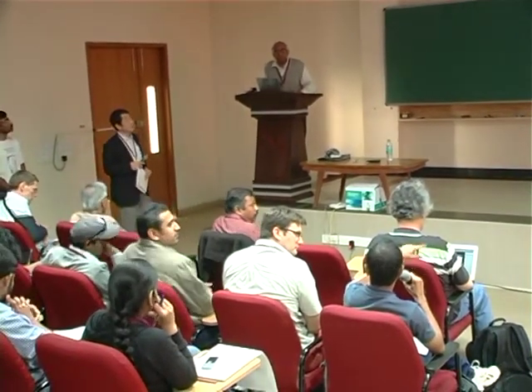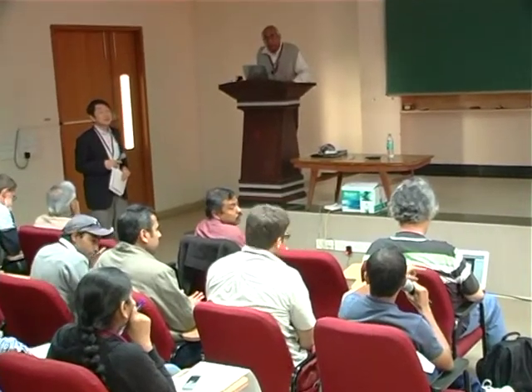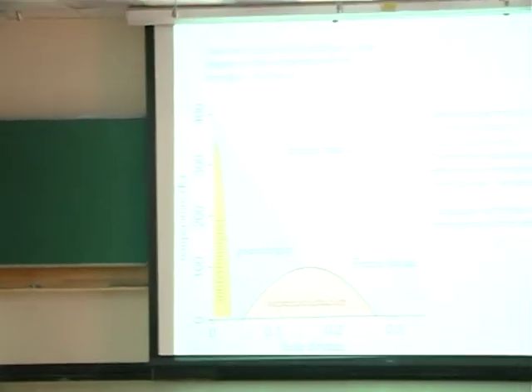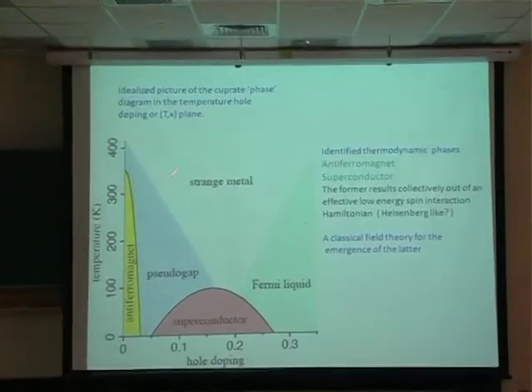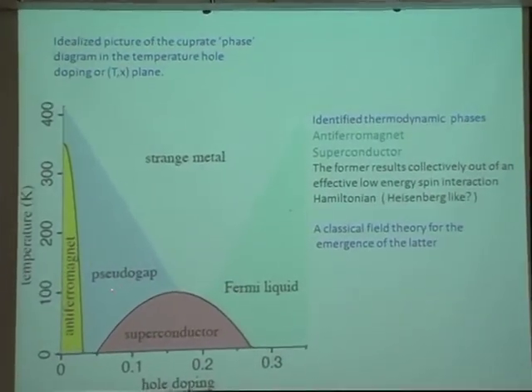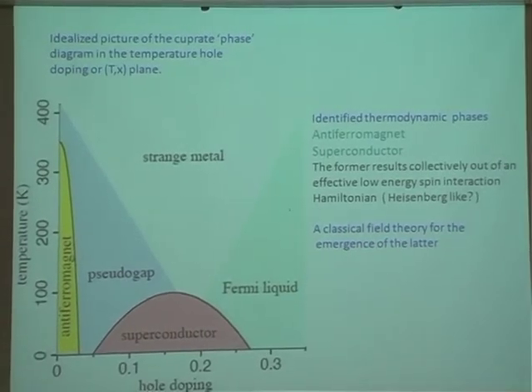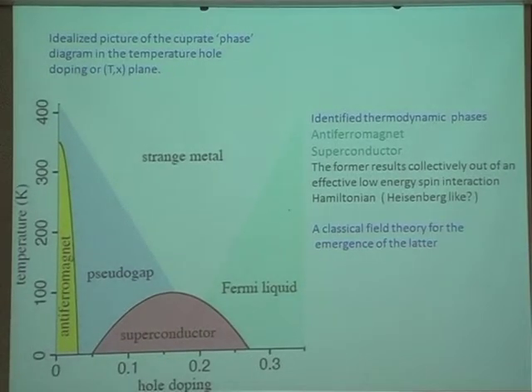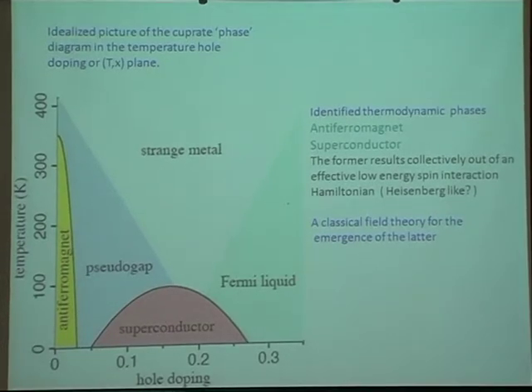Towards the beginning, you showed a phase diagram, where you have superconductivity as well as some antiferromagnetic phase. Was that schematic? In reality, yes. I mean, if you want, I can show a pretty picture, which is this. And this picture does show that there is an antiferromagnetic phase and there is a superconducting phase. So we really have nothing to say about this. We pretend that we are somewhere here. Because the holes are mobile, you don't have to worry about antiferromagnetic correlations. But yes, if you want a more comprehensive picture, you have to include those issues.